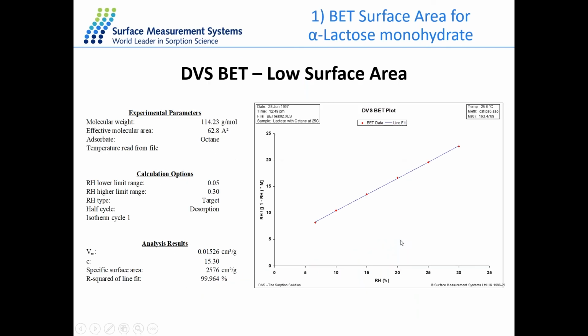And then we fit the lines with the BET equation from the previous slide, and we get this BET plot. From the slope and the intercept of this plot, we can then calculate the monolayer volume as well as the sorption constant of this material. And with the cross-sectional area of the octane molecule, we can then calculate the BET surface area of this lactose sample, which is about 0.26 square meter per gram.